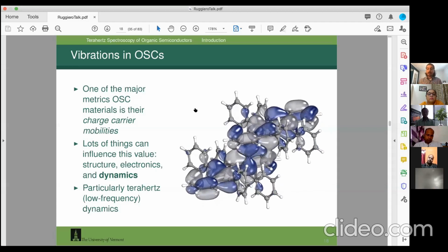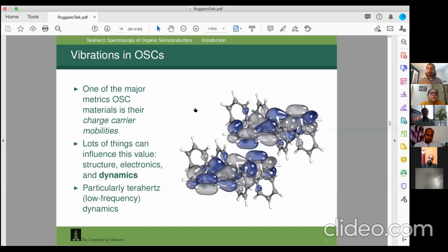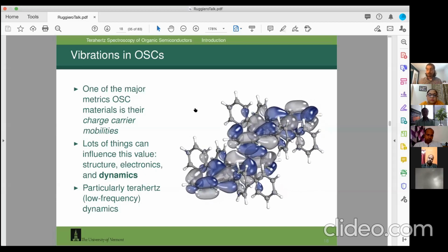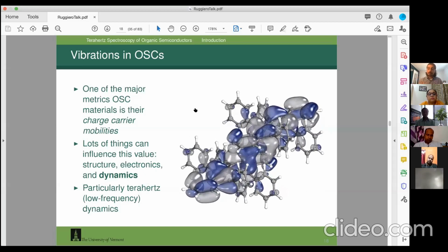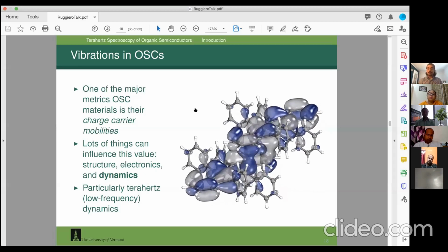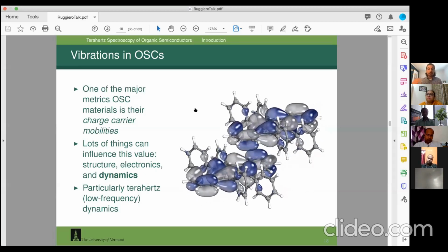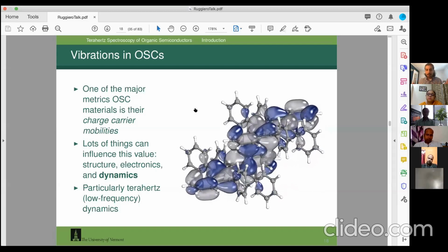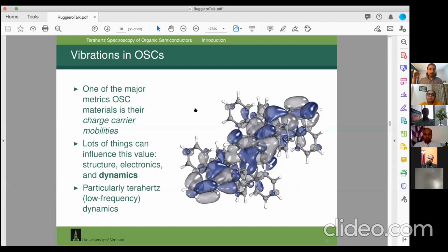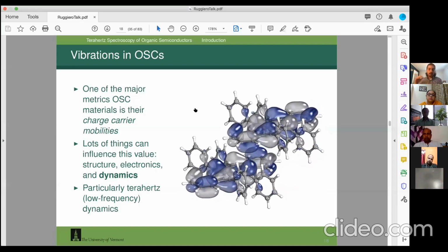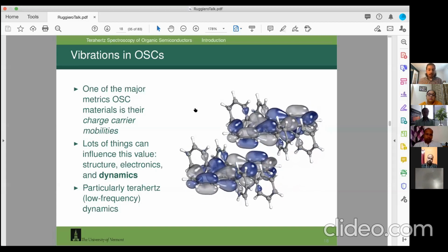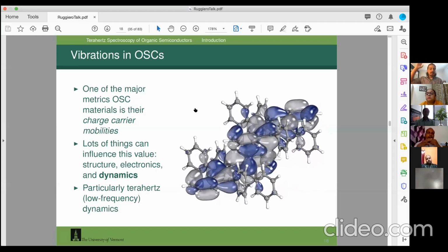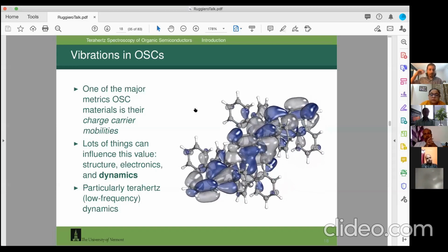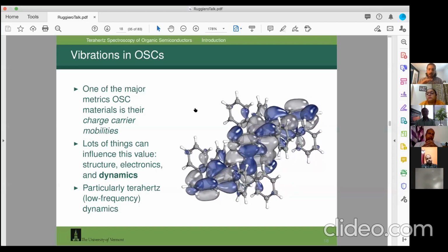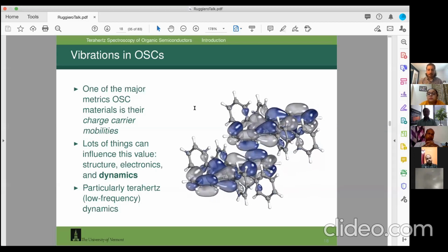And where that comes into play is scattering of free carriers off nuclear motion, or electron-phonon coupling. This is particularly true for the lowest frequency vibrations because they're very thermally active. So if we have a terahertz vibration of 20 inverse centimeters, thermal energy at room temperature is 207 inverse centimeters. So that terahertz vibration will be excited - 20 states will be excited - at ambient conditions. So this motion is really occurring at a large amplitude at ambient conditions.